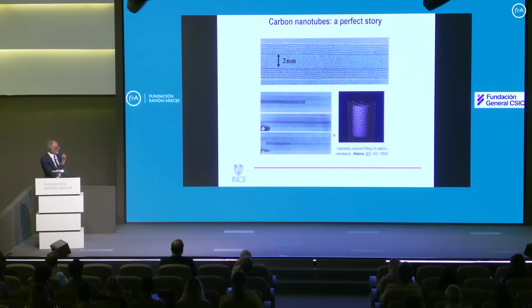And you can see, the dimensions are so small. If you look at that cylinder, the tube that you see, the inside of the tube is about 2 nanometers, and you can go all the way to 1 nanometer, right? And then there is this beautiful cylinder that goes for microns and microns and microns, sometimes into millimeters. So imagine a structure like this, such a tiny diameter, very large length, and such a beautifully perfect structure made from this hexagonal honeycomb lattice of graphene or carbon that has been known to us for a very, very long time, the graphitic structure.